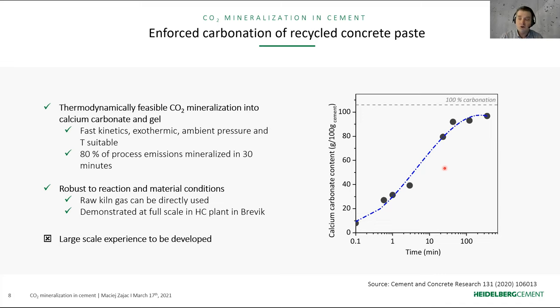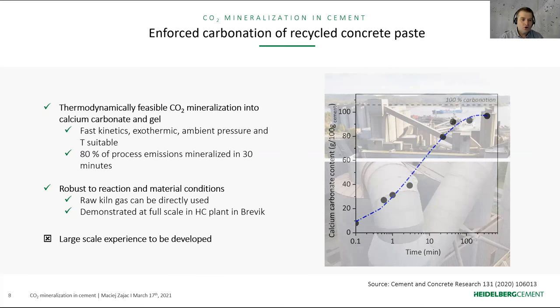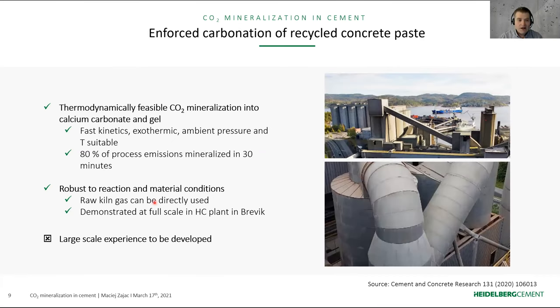It's a huge difference compared, for example, to the carbonation of magnesium silicates like olivine. What is very important as well is that this reaction is robust to reaction conditions. And so we can use the gases from the cement kiln directly to carbonate the material. We proved this during a plant trial at the Brevik cement plant that we conducted already 2 years ago. Of course, we are lacking real industrial experience regarding this process, and we are currently working on that.